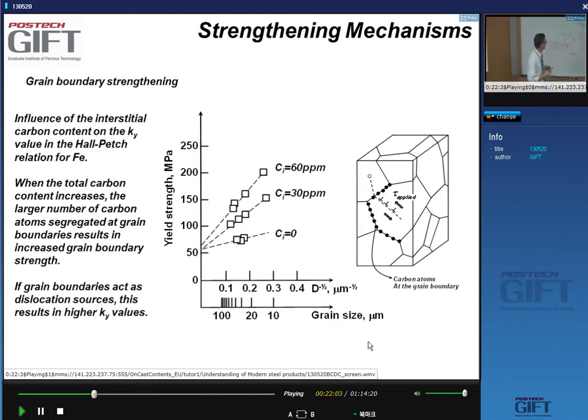There are no properties related to the composition or to the grain boundary itself. Well, it turns out that in steels, when we increase the carbon content, going from 0 to 30 ppm to 60 ppm, instead of having something like this, where the slope is the same but you increase the yield strength because of carbon strengthening, what you see is that all these points come together and the slope increases as I increase the carbon content.